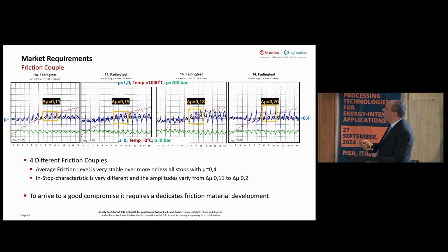Again, if you can hold 0.4, this is the line, is a good level. So this is what we want to have. Repetition of the same test with different pads again. Are all okay? Seems yes, but if you take a deeper look here, the delta mu, from the beginning to the end, is completely different: 0.1, 0.2, over 0.4. So it's important to have this more stable. Also for the ABS system, which has to control knowing the mu profile, it's better to have this type or this type, depends. But what I want to say is that it's not just the rotor that is important, it's also the system.